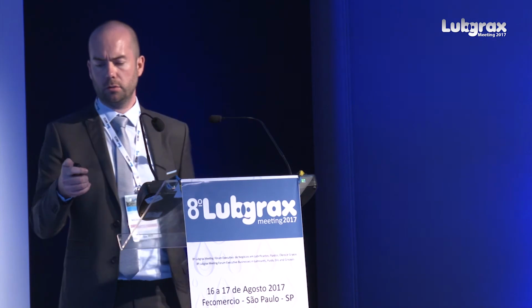Again, the MCT test will show that at temperature above 280 degrees C, you have a lower amount of residue with neopolyol esters.